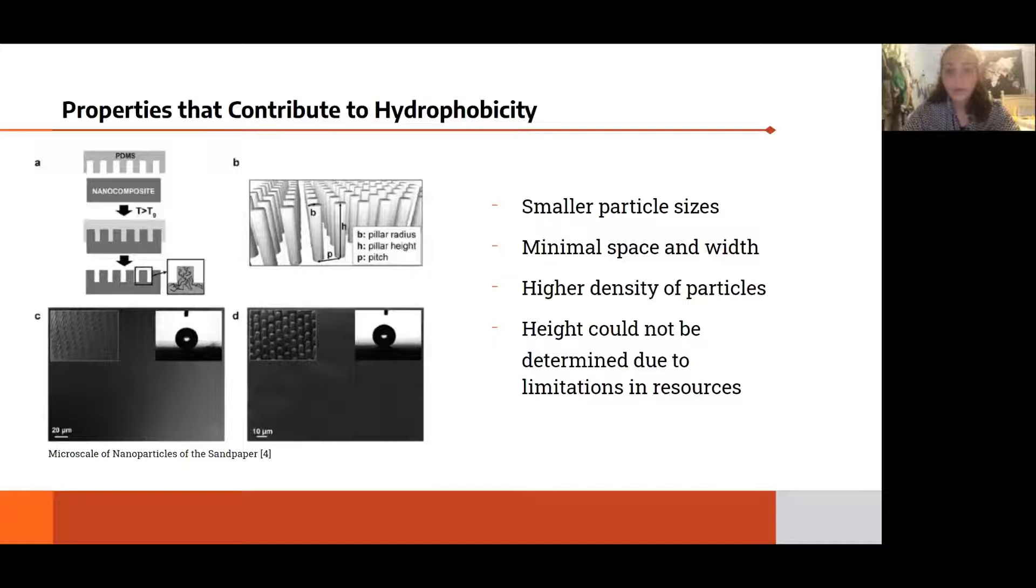For our purposes of this experiment, we discovered relationships between the sandpaper grade and hydrophobicity. We did this by looking at the micro level, the pillars, and their properties such as their height, width, and spacing. As the grit sizes of the sandpaper increased, the finer the surface and the smaller the particle sizes, decreasing the width and the space between each of the pillars.